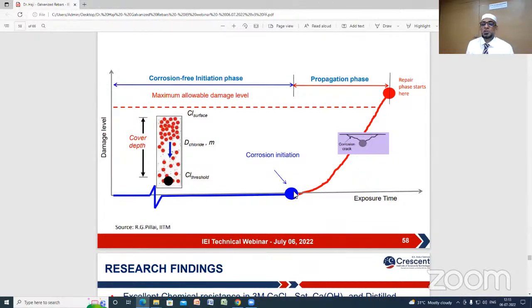In reinforced concrete, once corrosion initiation happens, the rate of damage is enormous. Within a short span of time, it will lead to the repair stage. So all our effort shall be towards the extension of the corrosion initiation. Fortunately, in galvanized rebars, since it performs well against carbonation and chloride penetration, the blue line is already extended.